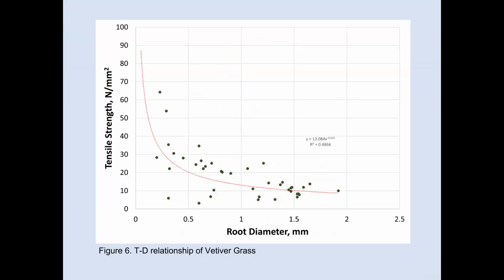The tension-diameter relationship for the vetiver grass is shown in figure 6. As you can see from the curve formed in the graph, the tensile strength decreases with increasing root diameter, and it follows the power law equation of the form f of x equals a x to the power k, which we can use to predict the strength of the root.